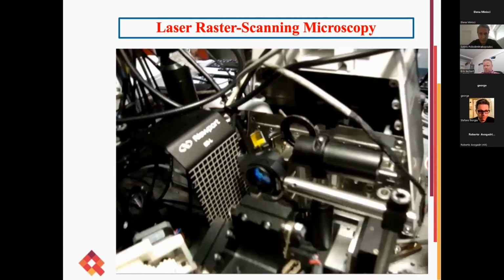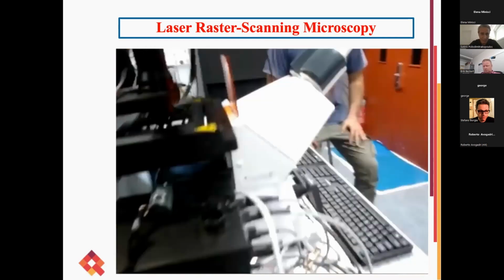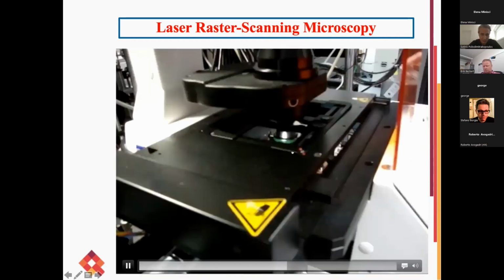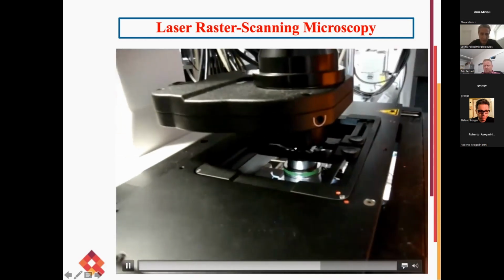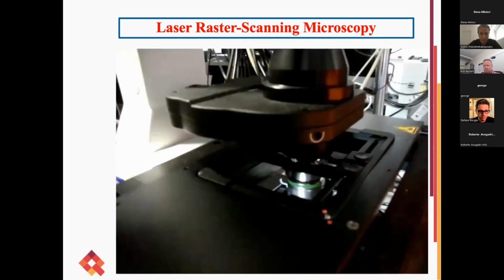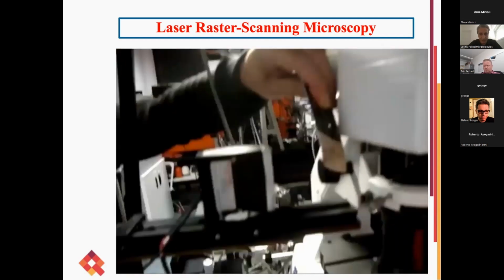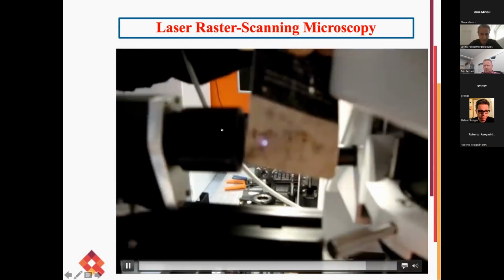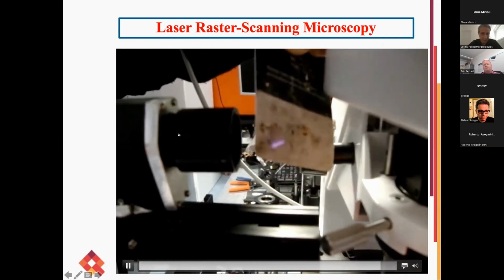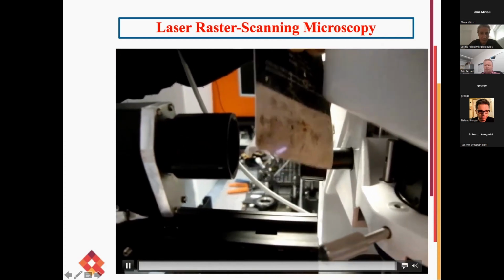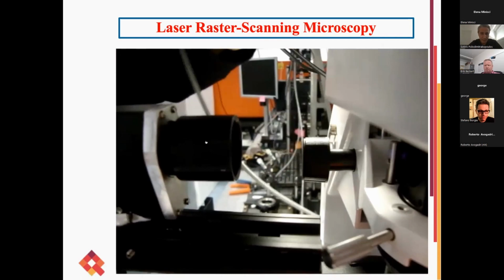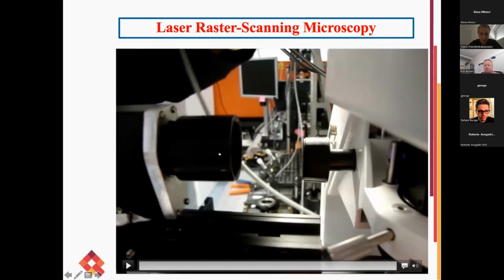And then this raster scan beam is focused, is reaching the objective lens of the microscope, and it is raster scanning the sample. So for every point of the sample, the signal is reaching the detector. This photomultiplier tube is taking a measurement, and we are going to have the creation of an image. And of course here we have placed appropriate filters in order to eliminate the laser and allow only the useful signals that we want to record to reach the detector.